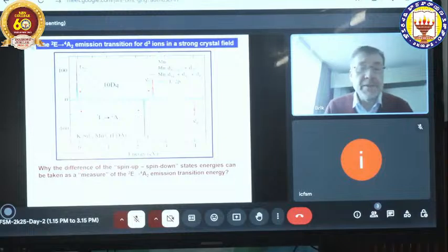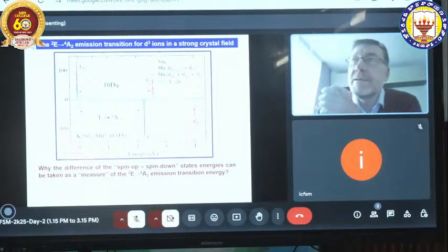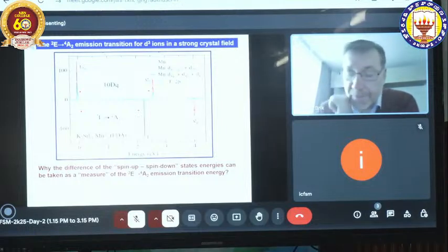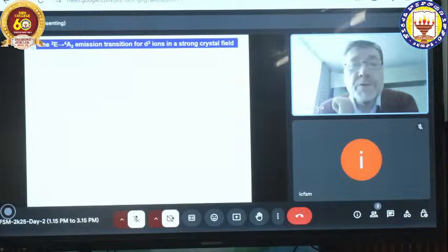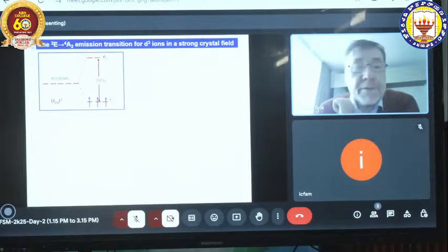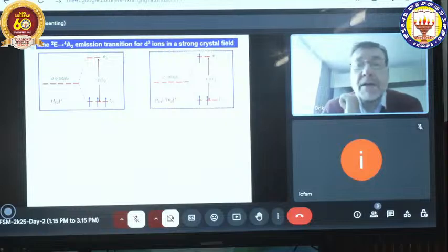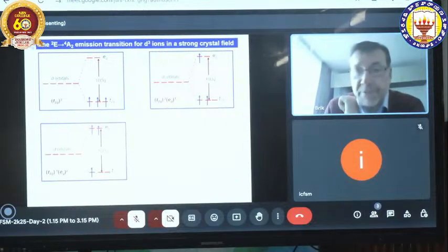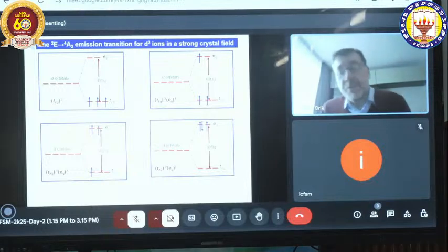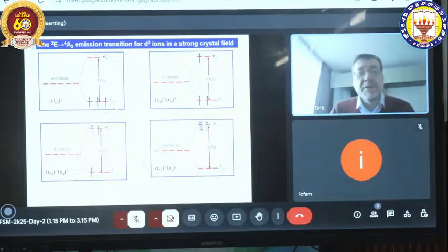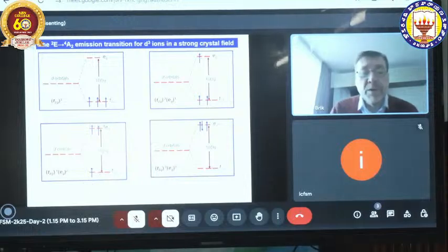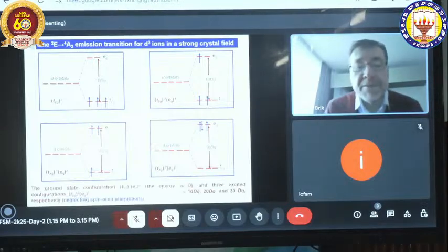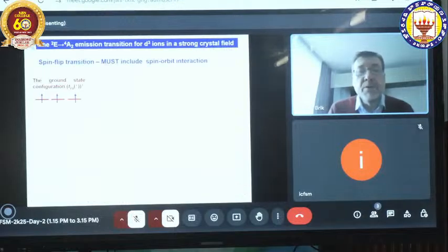Here is again an enlarged view of these density of states diagrams with the T2g, Eg levels indicated, and now I'm going to explain at least briefly why we do not get exact correspondence with experimental data. This is because of certain limitations of DFT theory. These are the possible configurations of the d3 configuration in a crystal field. We can have T2g spin up with 3 electrons, all the electrons here. We can have 2 electrons in Eg states, and we can have spin up, spin down states in Eg states. And then what is going on?